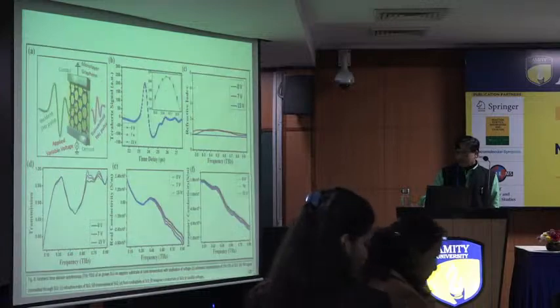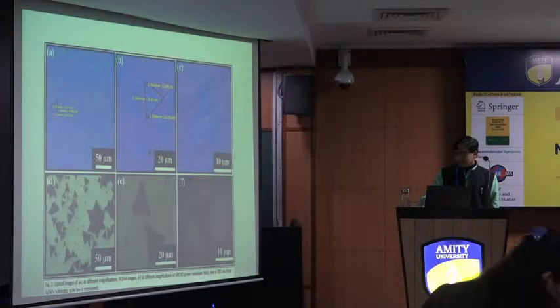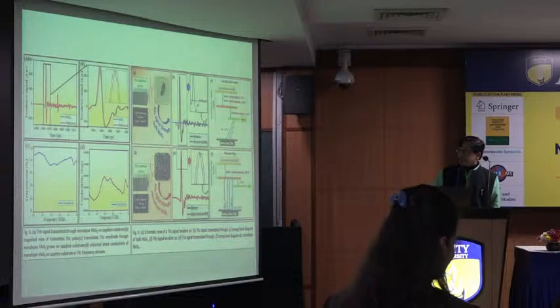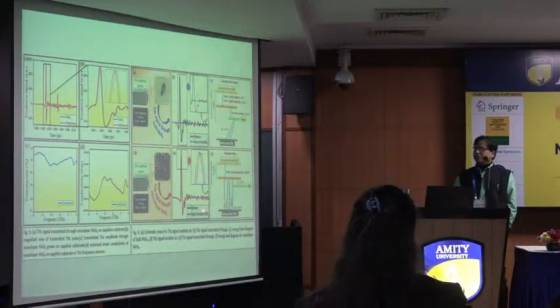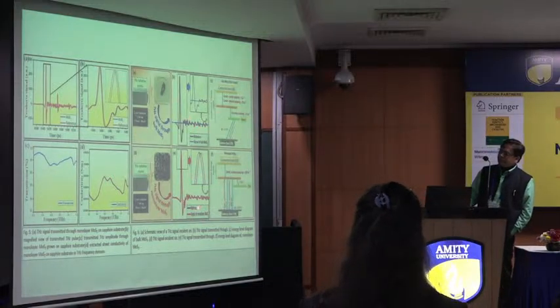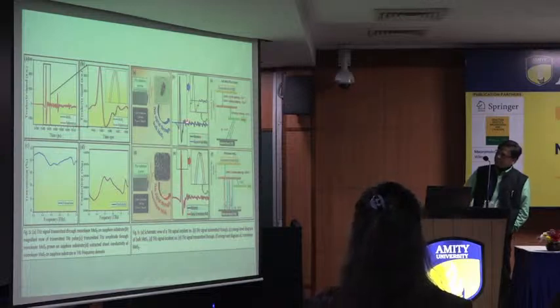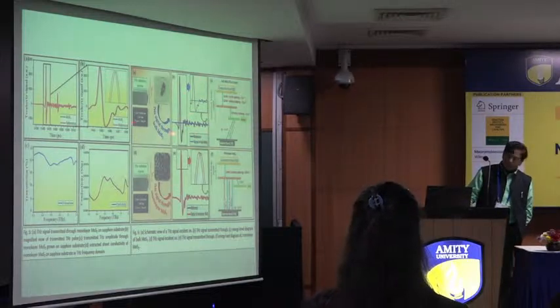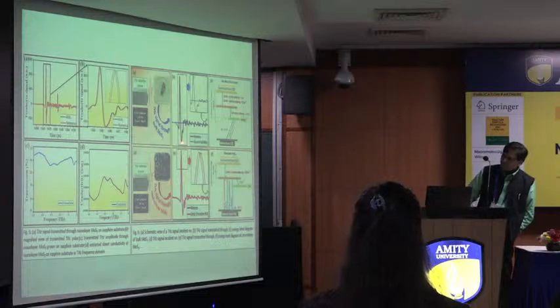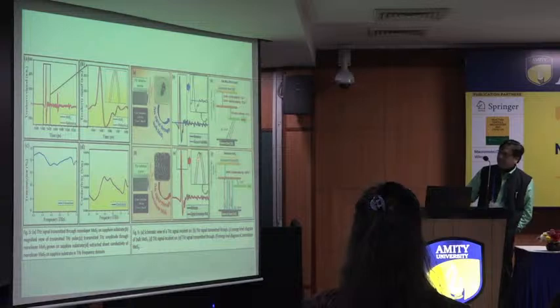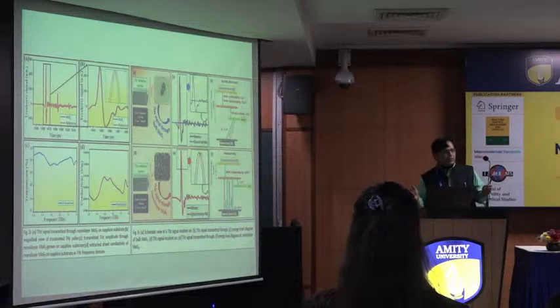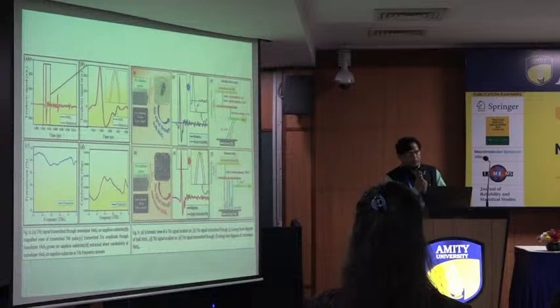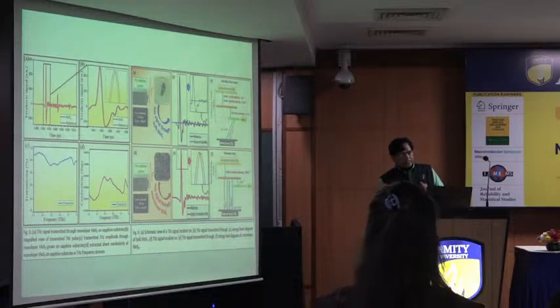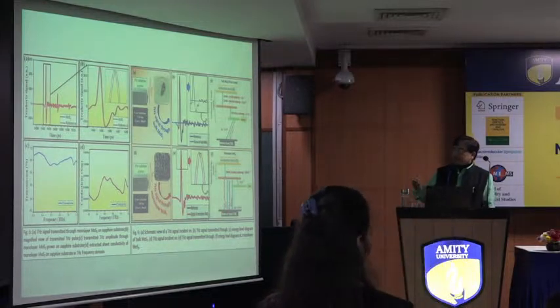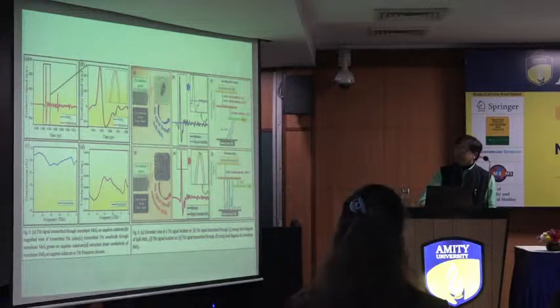Another area I am talking about is MoS2. You can see this result is very important. If you see the difference between the bulk and the monolayer, the absorption is very high in the case of the bulk, but in the monolayer there is only a very small shift and the change in intensity is almost negligible. That's why we are looking at the MoS2 and graphene heterostructure to make tunable terahertz with the best optimum efficiency for terahertz applications.